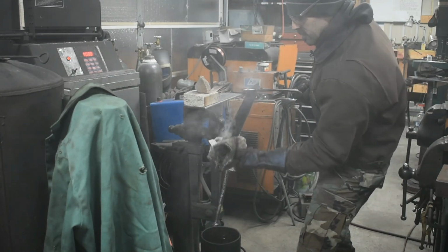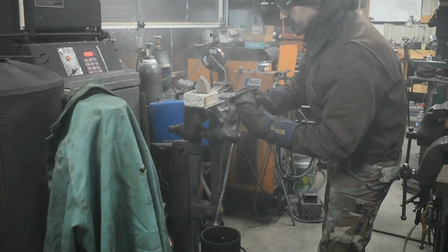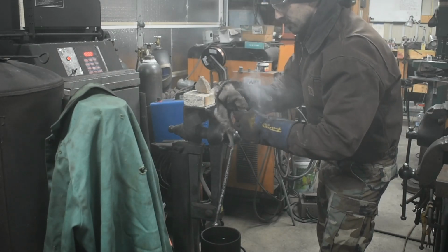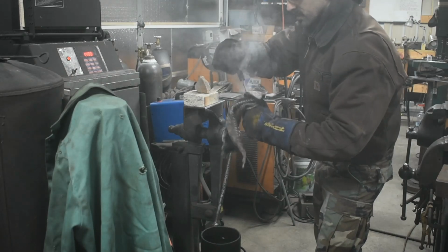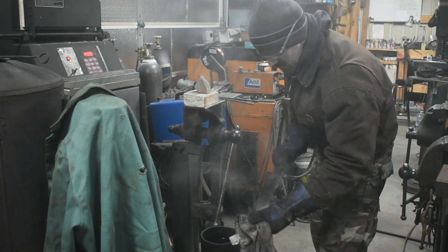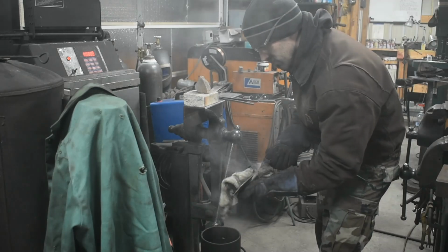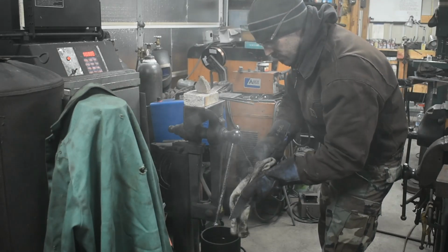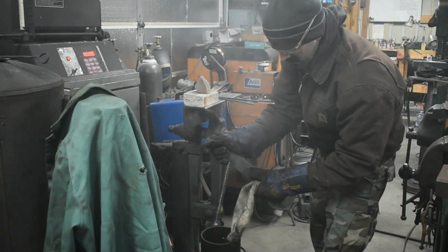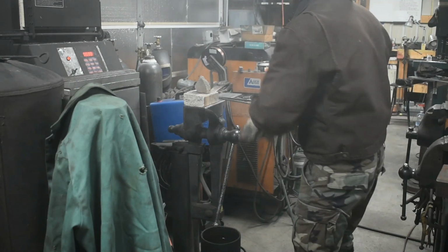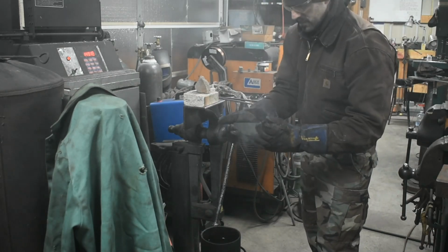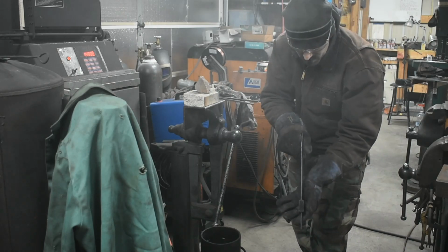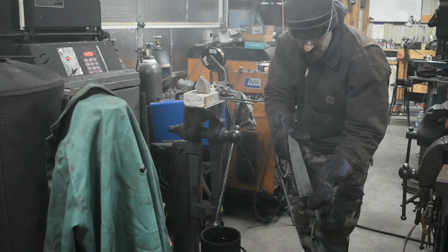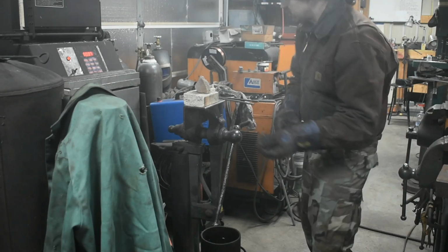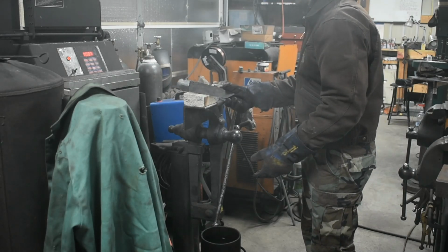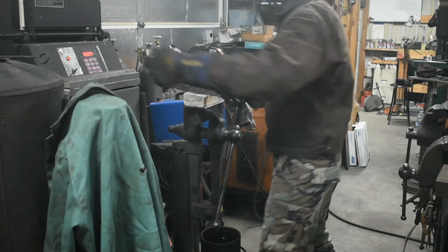Now I'm going to finish mopping that oil off. Got a pretty good scale break there. That's always a good sign when most of it slides off rather than sticks on. And I'm going to visually inspect it, make sure everything is straight. Didn't warp in the quench. If it did warp, it's still hot enough that I can tweak it straight with these heavy gloves on. So that one looked good right out of the oil.